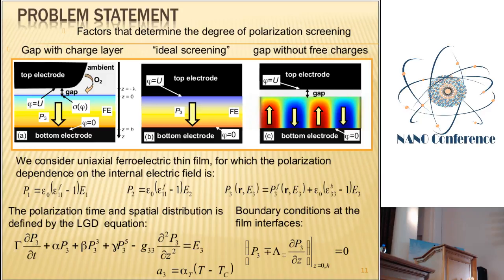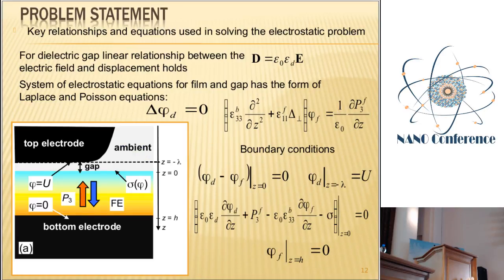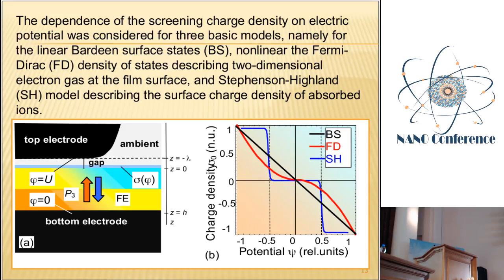Well, and further, I will consider three models. As I said, the model of linear screening, when the density of the surface charge depends on the applied electric potential. In this case, it will be overpotential because it will be different from the applied potential, in fact, in a linear way. This corresponds to the Bardeen surface state, for instance, or to imperfect electrodes. The next model is the Fermi-Dirac screening corresponding to 2D semiconductors like graphene or boron nitride. No, better to say graphene, because graphene is massless and for boron nitride it is difficult to say. And the third case is the Stephenson-Highland model of Langmuir adsorption. And my goal is to compare results for these three model cases.